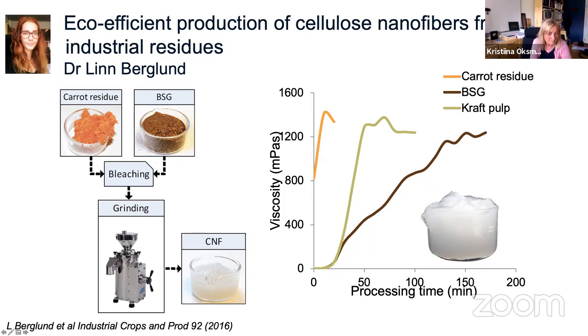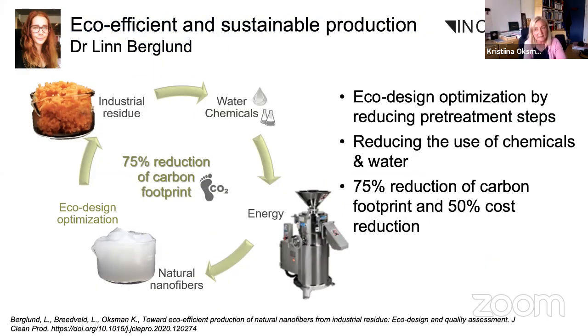And we also made eco design optimization by reducing a pre-treatment step. And we did that for this carrot material. And basically we reduced one step. We reduced the sodium hydroxide step, which is usually used to remove some of the hemicelluloses. So we didn't do that at all. We just made this bleaching, and by that we could reduce the use of chemicals and of course water. And it was shown that this reduction of this step reduced the carbon footprint by 75% and the cost by 50%. So that was a very efficient way to make this process even more eco-efficient.